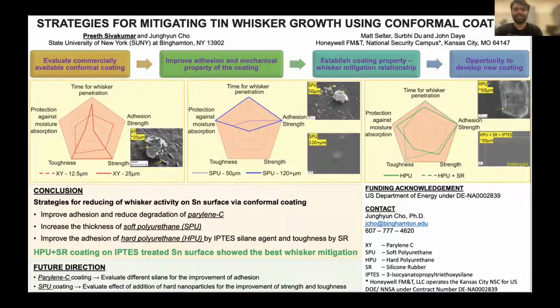Thank you, James. So my research is mostly to study the tin whisker growth mitigation using conformal coating. Based on all my work, we have come up with some strategies for mitigating tin whisker growth using the conformal coating. What we did is first we evaluated some of the commercially available conformal coatings, then tried to improve their adhesion and mechanical properties. And based on the results which we got, we tried to establish a relationship between the coating property and the whisker mitigation behavior.